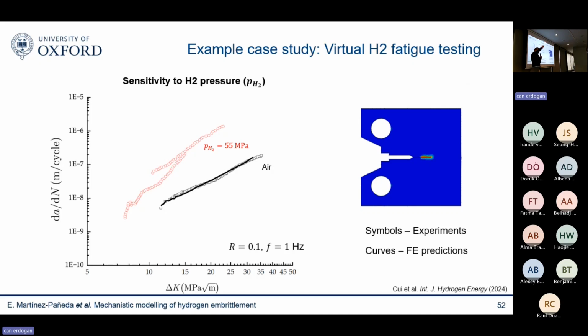We can use that Sieverts' law that I showed you before. We convert 55 megapascals into a hydrogen concentration. We impose that as a boundary condition. We do not touch anything in our model. We don't recalibrate anything. We do not change any of the parameters, and we run the simulation. And this is what came out of the simulation. So we were quite happy.